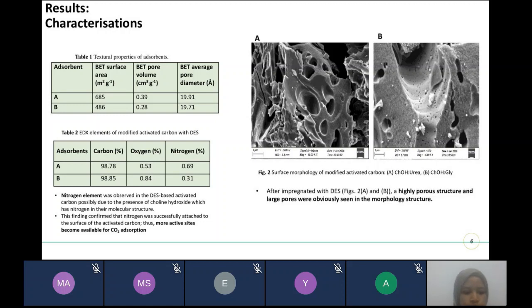As can be seen in Table 2A and B, nitrogen element was observed in DES-based activated carbon, possibly due to the presence of choline hydroxide, which has nitrogen in its molecular structure. This finding confirmed that nitrogen was successfully attached to the surface of the activated carbon, thus more active sites become available for carbon dioxide adsorption. After impregnation with DES, in Figure 2A and B, a highly porous structure and large pores were obviously seen in the morphology structure.